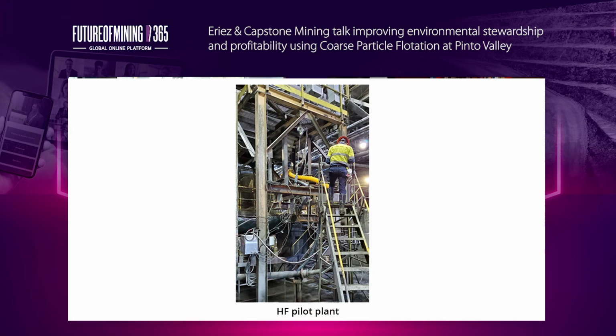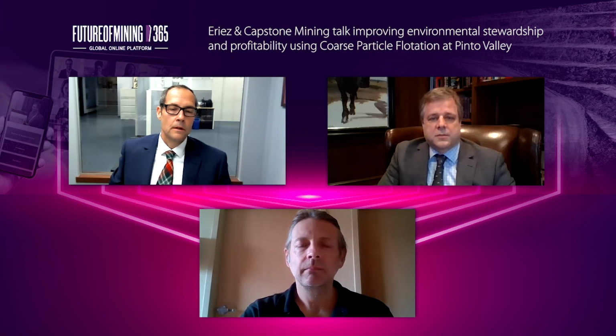This was repeated at the site with the HydroFloat pilot plant. A representative sample from the tail was taken through an Eriez crossflow and HydroFloat, and the results achieved 6 to 8% increases in copper recoveries, exceeding the company's expectations for a 6% improvement in recoveries. As a result of this work, we are conducting a feasibility study to implement this technology.